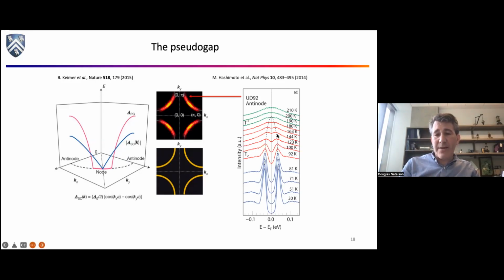So here's an example of some data. The details aren't particularly important, but the bottom line is when the system's superconducting, a bunch of the electronic states near that Fermi energy get eaten up, and you open up what's called a gap. That's why there's this big dip at the Fermi energy. That's what in the blue case, this is in the superconducting state. And the important thing to realize is that there's a dip that starts forming at temperatures a factor of 2 higher than the superconducting temperature. So something weird is going on to the system way before it ever starts superconducting. This dip here is called the pseudo gap.